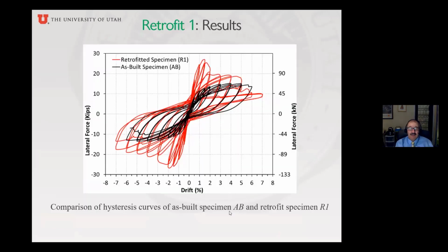So what happened? This is what happened if we compare it to the first test. You see we improved the lateral force from 15 kips up to about 25. We improved a little bit the displacement capacity, but not much. But unfortunately here, I'm going to show you this drop is because one of the anchors actually pulled out from the hole where it was.